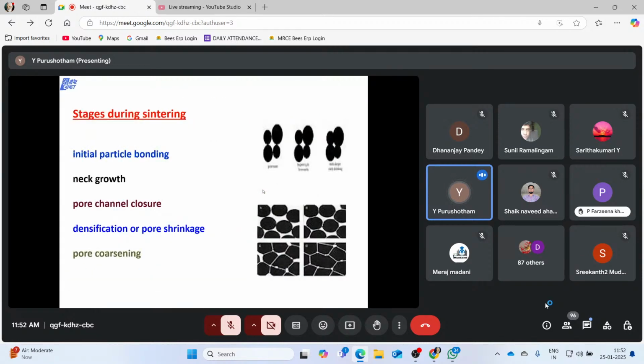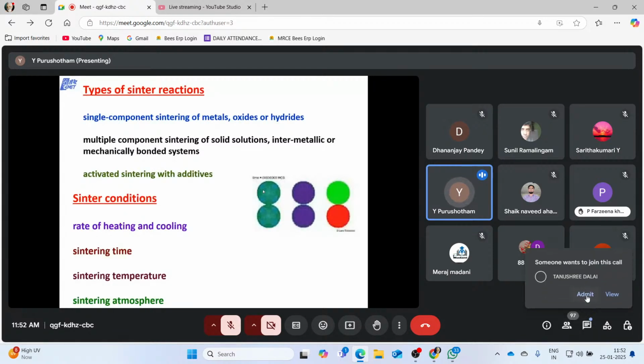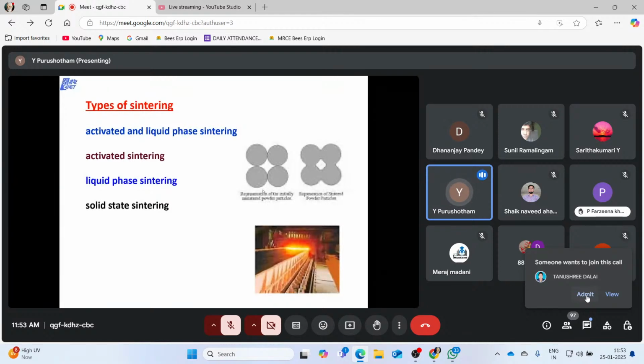There are different stages during sintering: initial particle bonding, neck growth, pore channel closure, densification or pore shrinkage, and pore coarsening. How will pore coarsening take place? If you are giving more time for sintering, then first densification and shrinkage will take place, and after that the pores will be coarsened. There are also different conditions: rate of heating and cooling, sintering time, sintering temperature, sintering atmosphere. These are all research topics. We are all very well aware of these sintering conditions, and there are types of sintering: activated, liquid phase sintering, solid state sintering.